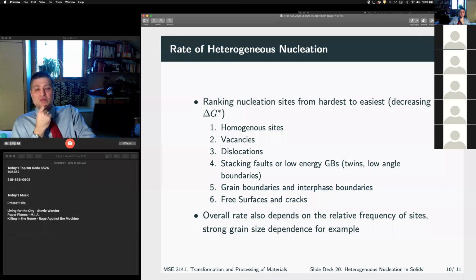Okay. The overall rate is also going to depend on the relative frequency of sites, right? So you'll see that we have a large dependence on the grain size, because the grain boundary surface area is dependent on what the grain size is. If we have a smaller grain size, we have a lot more grain boundaries in our sample, right? And we also have to move our solute a lot less distance to the grain boundary. So our nucleation rate in a fine grained system is going to be much higher than in a large grain system because of the amount of grain boundary surface area that we have.